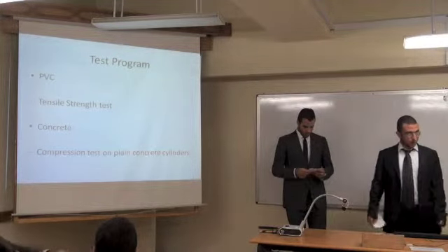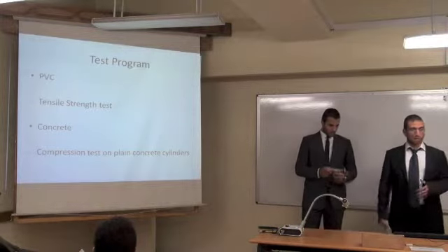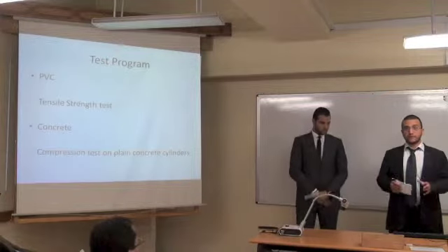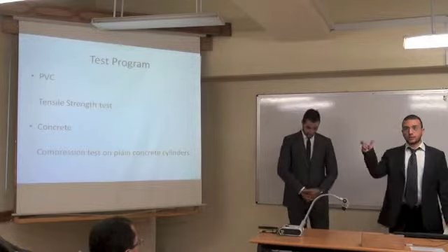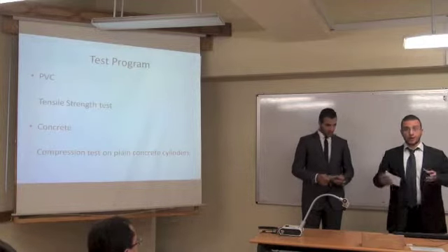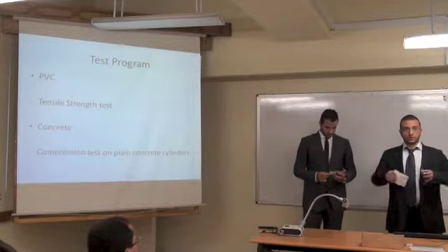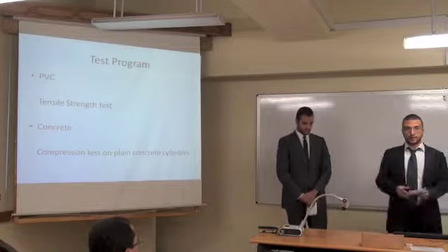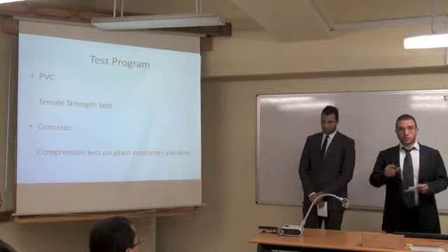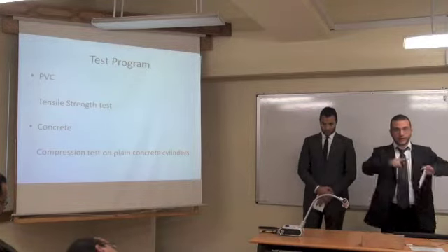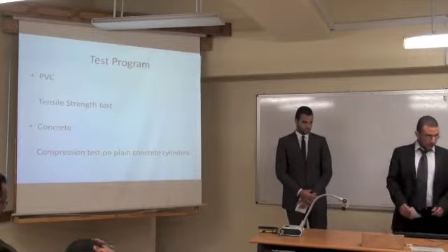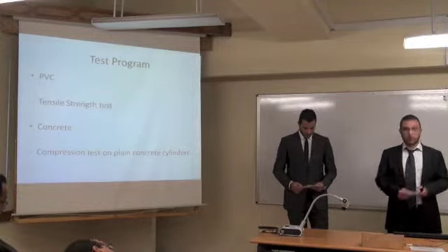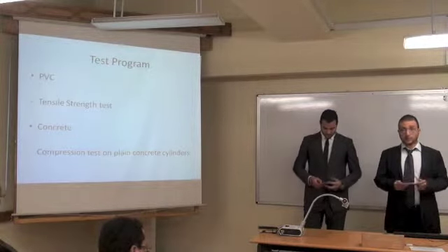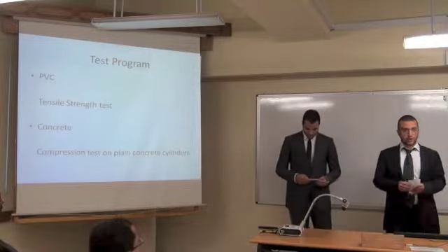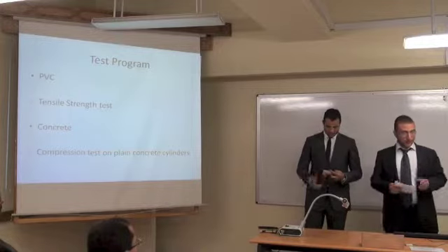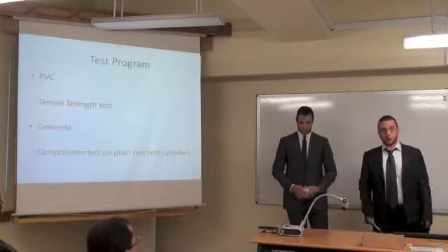Also included in the test program, we need to conduct tensile strength tests on the PVC tubes, because the PVC tubes are subject to tension as a result of the reaction of the confinement from the concrete core. When the concrete core is confined, it exerts a reaction on the PVC tubes, which causes tensile hoop stress all around the PVC tube. For the concrete, we aim for specific strengths through the mix design, as we still need to test the actual strength of the concrete batches. So we're going to create 3 cylinders to test the actual strength of the concrete samples.